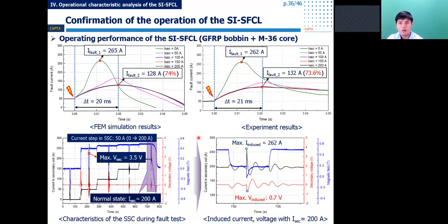In the fault testing, the fault limiting characteristics of the SI-SFCL were confirmed with different secondary operating currents and then compared with the FEM simulation result. As you see, the experiment result was similar to the FEM simulation result. With the secondary current of 200 ampere, the fault current was limited up to 73.6%. During the fault test, the induced current and voltage in the secondary coil were quite low, which didn't affect the DC bias current source and secondary coil operation.